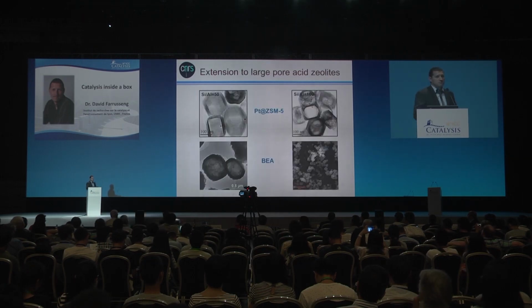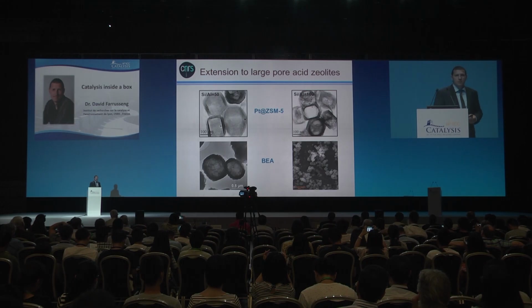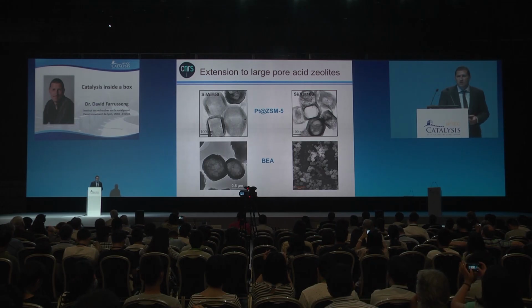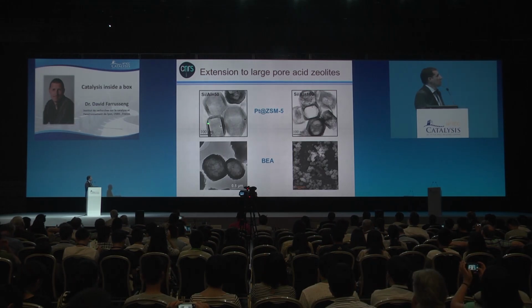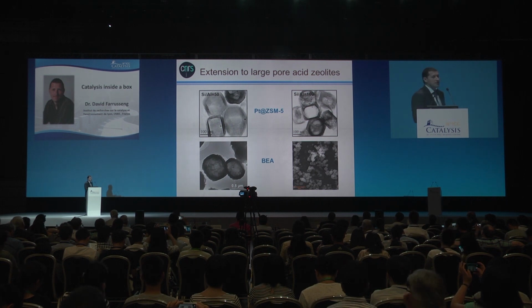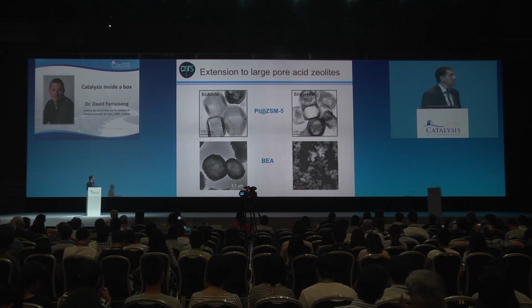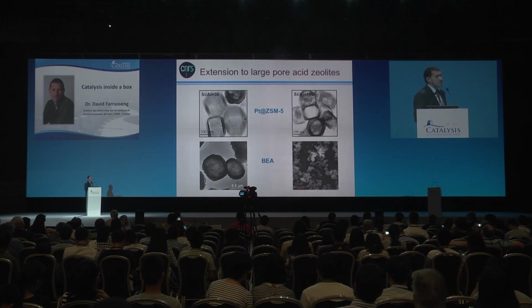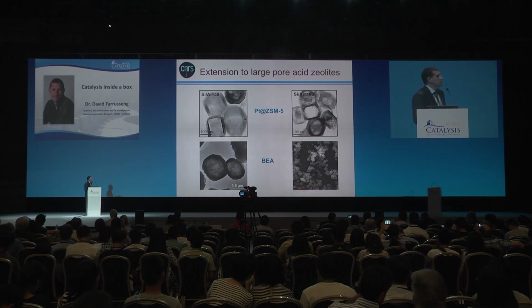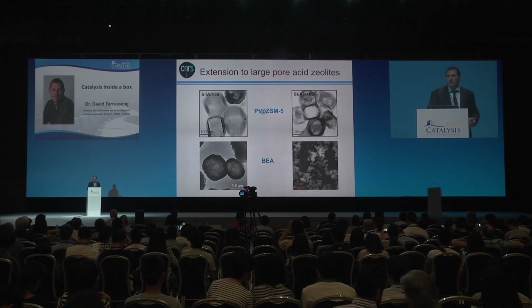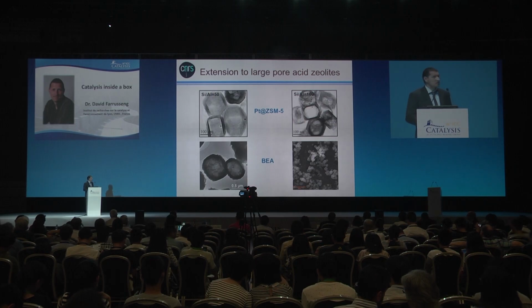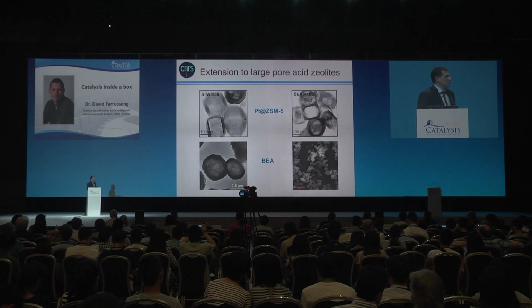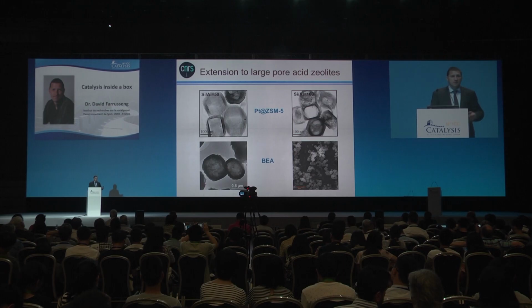Another main avenue we want to explore is to add a catalytic function to the zeolite membrane. And this can be achieved by adding aluminum in the zeolites, yielding here ZSM-5. And you can see here pictures of platinum nanoparticles encapsulated in ZSM-5. We're going to apply that for bifunctional catalysis, obviously. And here at the bottom, you can see that we have very recently managed to make hollow beta zeolite that will also be applied next in catalysis.